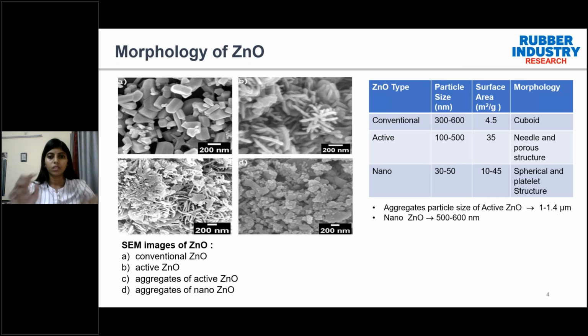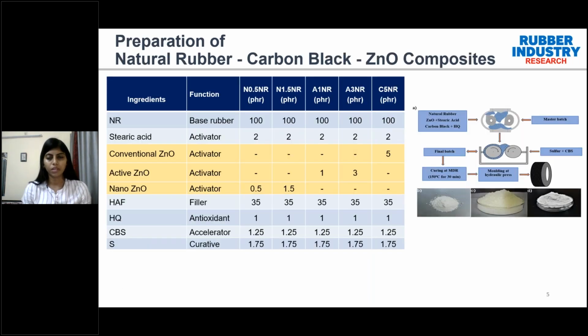Coming to the preparation of the natural rubber carbon black zinc oxide composites, we used nano zinc oxide from 0.5 to 2 phr, like 0.5, 1.5, and 2 phr, and active zinc oxide from 1 to 5 phr. The conventional zinc oxide at 5 phr was taken as the reference sample, that is C5NR. The nano zinc oxide compounds are termed N.5 and N1.5, and the active compounds are named A1NR and A3NR. The master batch preparation was done in the Brabender Plasticorder, and the final batch was prepared on the two-roll mill.